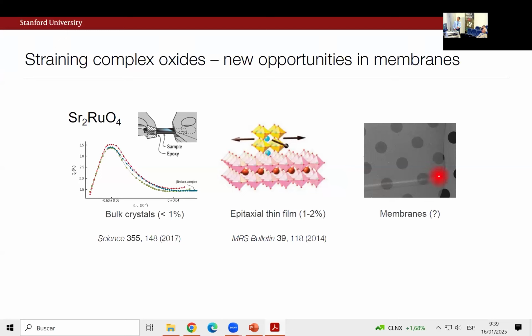So I'm showing you here, if I remember correctly, something like a 4 or 5 nanometer thick strontium titanate membrane. This is a silicon nitride grid. These are 2-micron holes. And what's very interesting is that this is a very brittle ceramic, right? If you've ever played with a substrate, it's brittle. If you're a theorist, let me say, it has the macroscopic mechanical response of your ceramic coffee cup. You can't really stretch it. So it's characterized by brittle fracture.